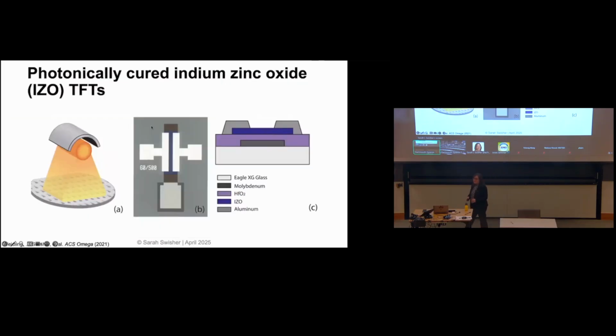Okay, all right. So this is a picture of one of the indium zinc oxide thin film transistors, or TFTs, that we've made. So here is the cross section. You can see this is the molybdenum as the bottom gate. That's molybdenum because it's got really, really good absorption. So it's going to absorb that energy, and it's going to heat this blue layer. That's my semiconductor. And after I've done the heating, I process that semiconductor and I deposit my source drain on top. And we can make transistors this way.